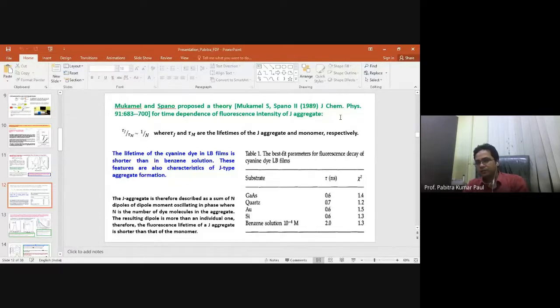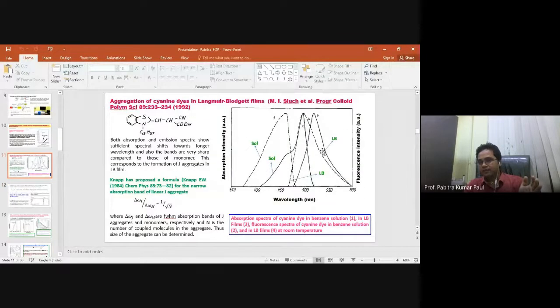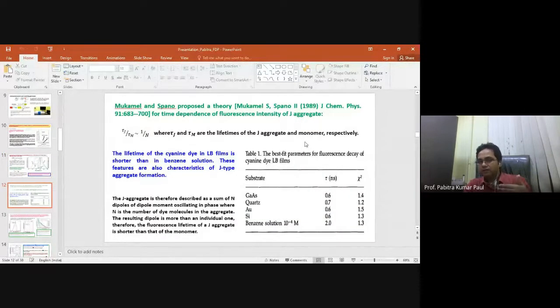It is published in the Journal of Chemical Physics, and it concerns the dependence of the fluorescence intensity. J aggregates also fluoresce, so we are concerned with what the fluorescence intensity of the J aggregates depends on. They proposed a model that tau J by tau M, where J stands for the J aggregate and M for the monomer, is approximately of the order of 1 by n, where tau J and tau M are the fluorescence lifetimes of the J aggregates and the monomer respectively. So the lifetime of this studied cyanine dye in the LB film is shorter than in benzene solution. These features are also characteristics of J-type aggregates.